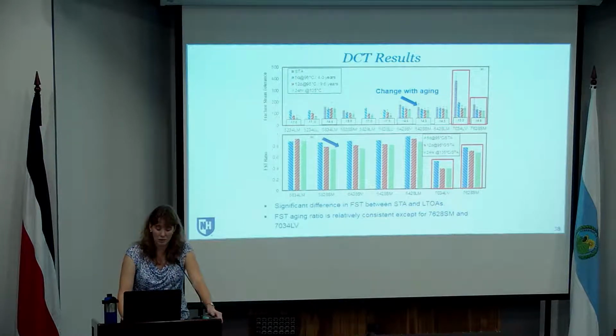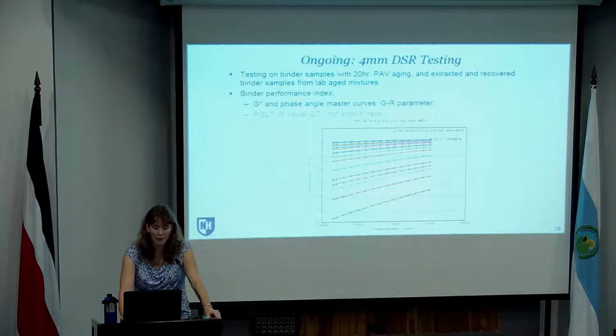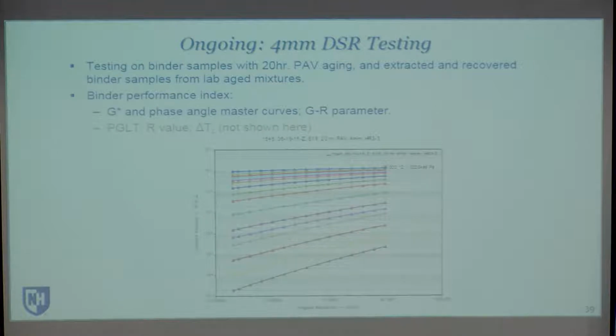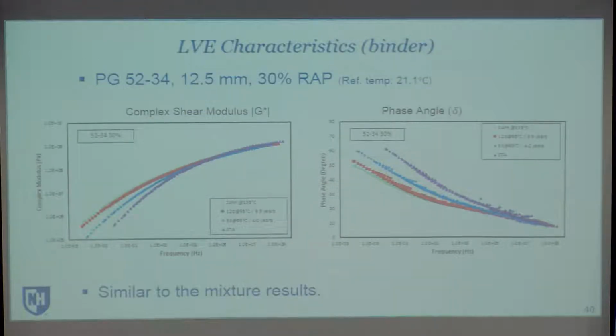So that's all the mixture testing. Ongoing work that we're performing right now in the laboratory is looking at binder testing on extracted and recovered materials from these different mixtures. So looking at the different aging levels as well. So in terms of the 4mm DSR testing, that allows us to do the wider range in terms of the viscoelastic characterization for the different binders. So again, just an example of some of the results that we're getting.